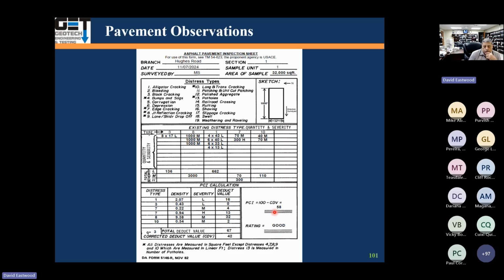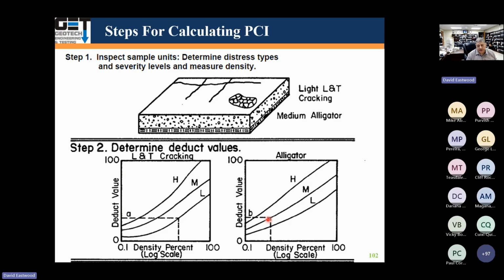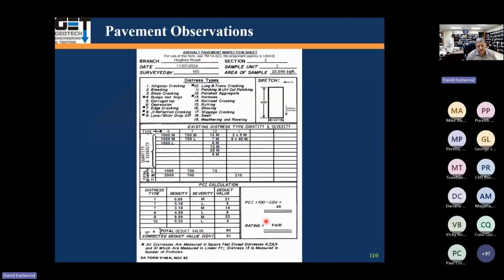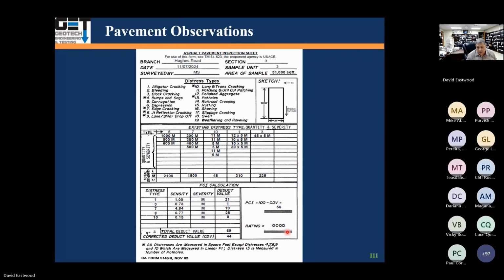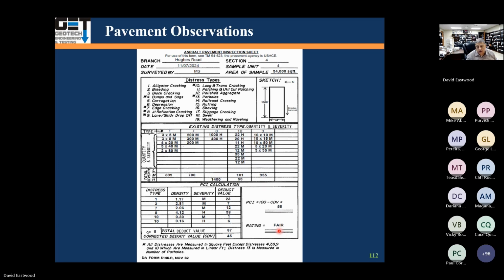Okay. So we basically took that pavement and then put it in 7 segments. Here's another 1,000 feet by 22 feet. Went through all the cracking and stuff like that, density, and we got a corrected deduct value of 51. We subtract that from 100, you get 49. That means that this segment has got a rating of fair. The next one is 31 feet by 1,000 feet segment. We got a PCI of 56, which means this section has got a rating of good. Here's another one, a segment 34 feet by 1,000 feet. Your PCI is 55. That means fair.